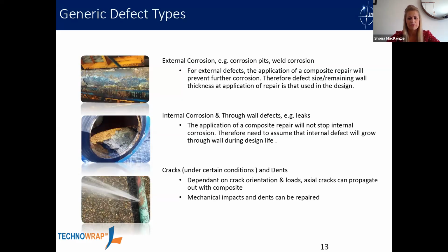So generic types of defects. We can cover most types of defects essentially. External corrosion is the standard application for a composite repair. Obviously the application of that composite will prevent any further corrosion. And so the defect size or remaining wall thickness at the time of that installation is used in the design itself. We also can look at internal corrosion and through wall defects or leaks.